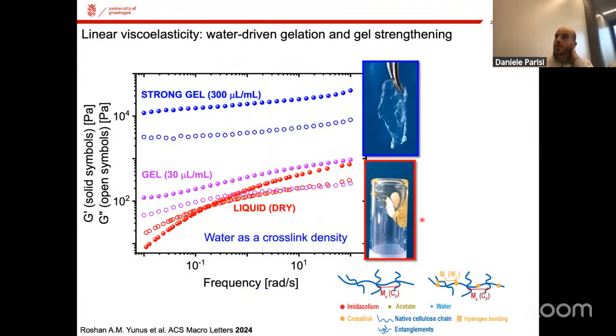So we could look at the same thing rheologically. So we start from a dry solution. So we have a liquid. We are seeing in this plot G prime, which is the elastic contribution to the total response, and G double prime, which is the viscous contribution to the total response. And here in the x-axis, we have the oscillation frequency. So at high frequency, G prime is larger than G double prime, so it's a viscoelastic solid. But then at very low frequency, or at large relaxation times, the inverse of the frequency, the material becomes a liquid.